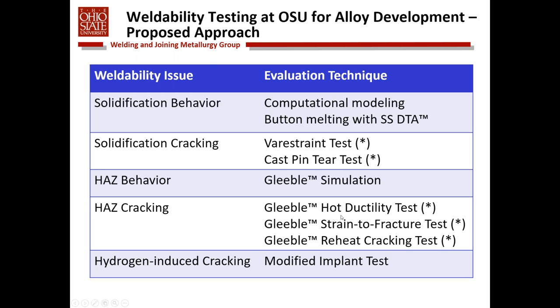And I'm going to describe briefly three tests that we use at OSU to evaluate various forms of heat affected zone cracking. And finally, hydrogen induced cracking is important in structural steels, particularly high strength steels. And we have developed a modified implant test. This is a test that was originally developed at the French Welding Institute by Henri Grandjean back in the 50s and 60s. And we use this test because it uses just a very small amount of material, basically small pins that are loaded under appropriate conditions to evaluate hydrogen-induced cracking. So I'm going to spend a little bit of time talking about cracking behavior and heat affected zone behavior of the tests listed here in this particular chart.